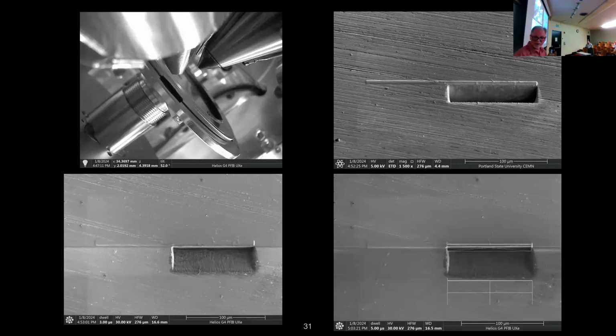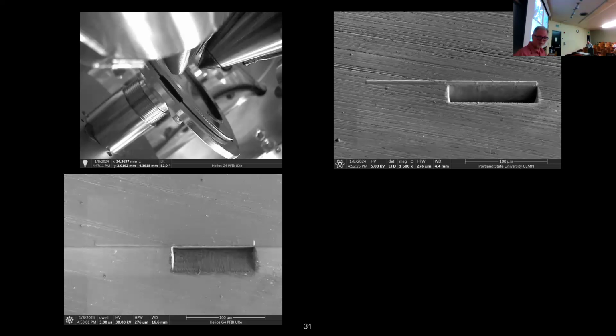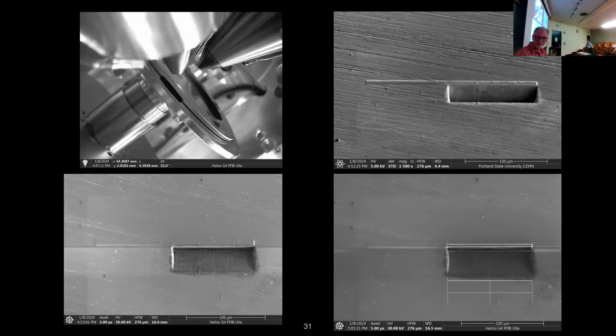And then we can see here where I did a little bit of polish to make it better. This prior image, I didn't quite get clear to my protective cap. That was intentional. I like to leave a little bit of space when I'm doing a high current mill. That's a 100 micron wide mill. I did that one at, I think, 200 nanoamps, if I remember correctly. And then I did a little 15 nanoamp polish there.